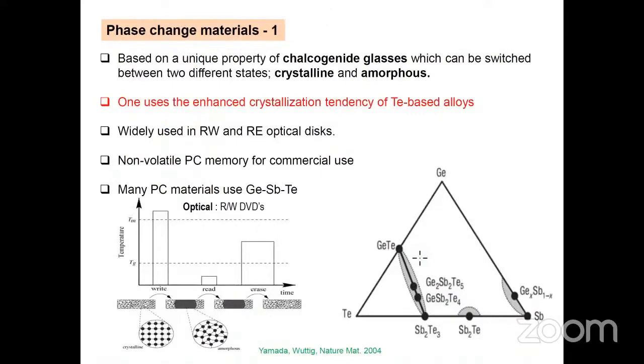So maybe I'll go a bit faster on this slide because you already heard about it. The issue of phase change is based on the unique properties of those chalcogenide glasses. You're basically switching between a crystalline state, which has a low resistivity, which is semiconducting at low temperature, with an amorphous state, which has a high resistivity. And the difference in resistivity or even in optical contrast can be up to 6 orders of magnitude, depending on the composition, on the film quality, on nucleation site formations, etc. And so this is widely used in optical disk writing and data storage.